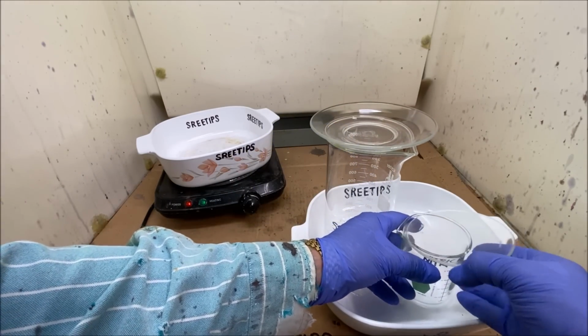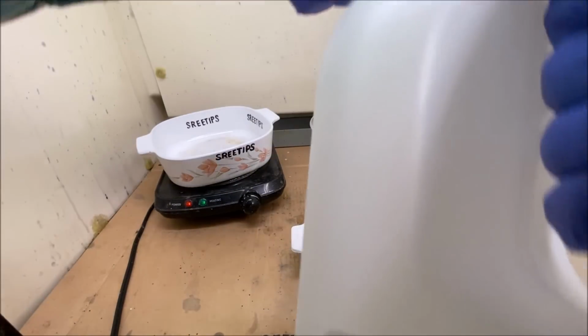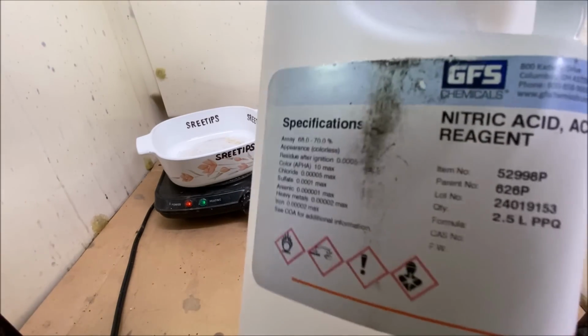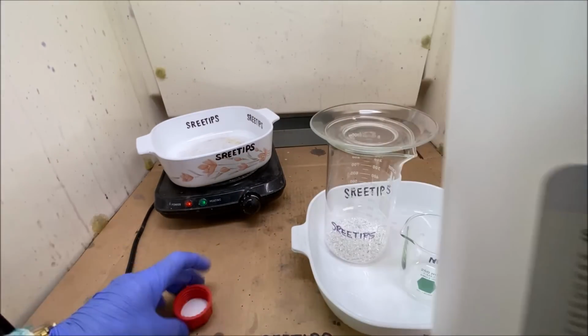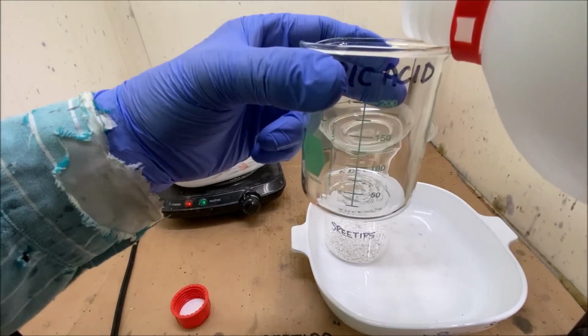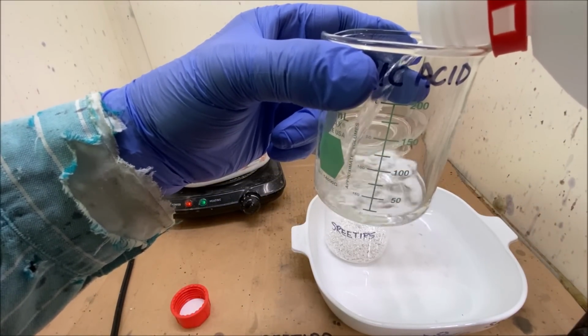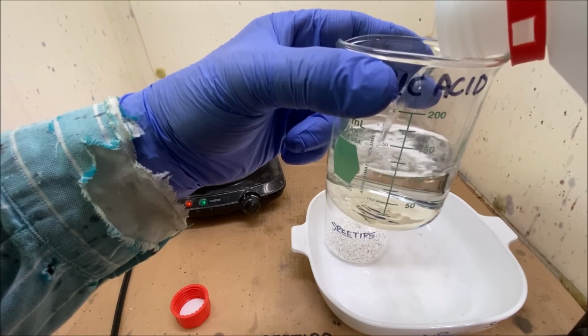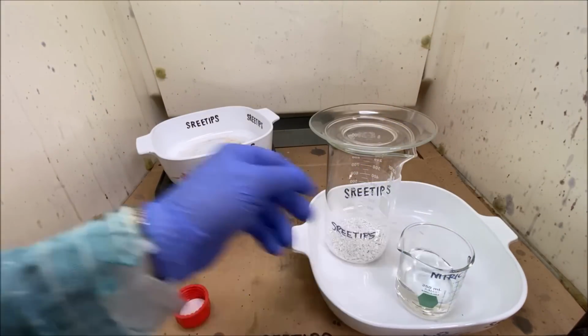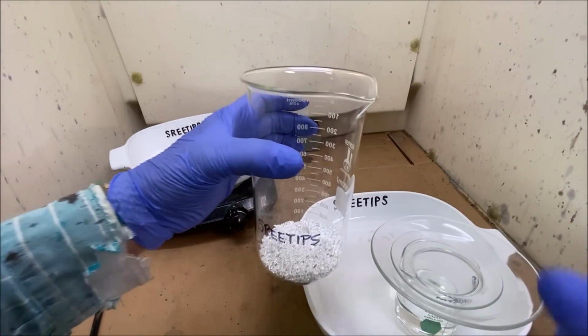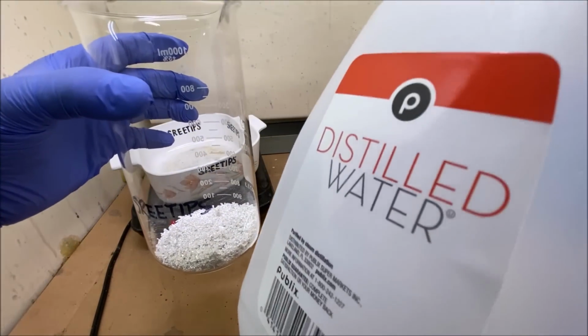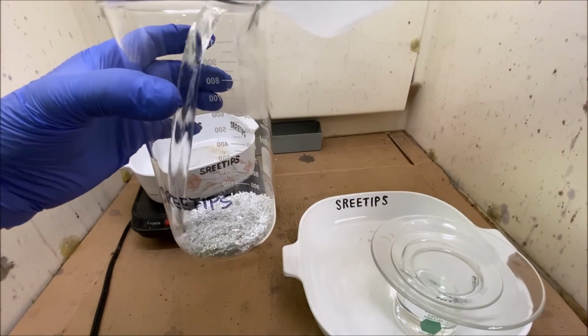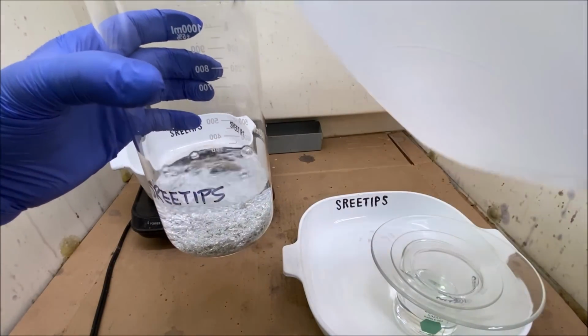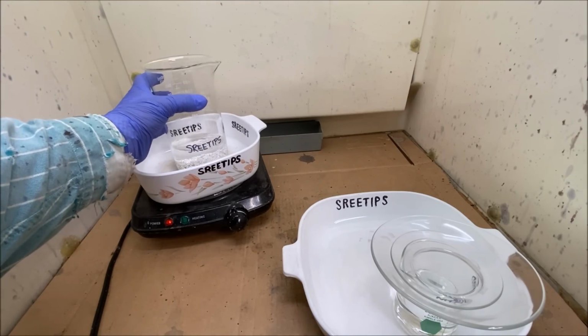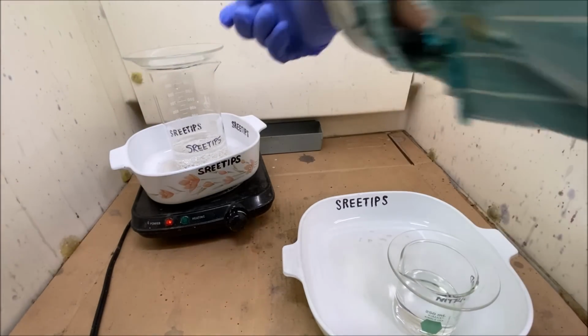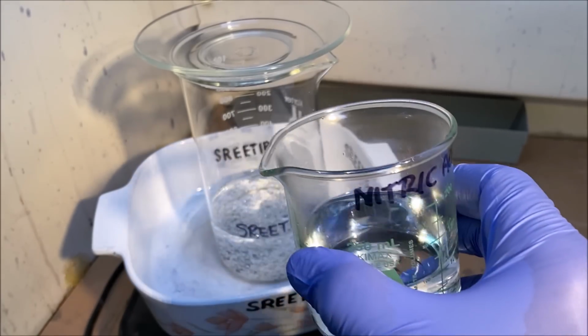And I'm going to measure out about 100 milliliters of nitric acid here, about 100 milliliters. That's a little over, that's just fine. Now what I'll do is add some distilled water to about the 300 milliliter level. We're going to set this up on the heat over here. Start adding some nitric acid in here.